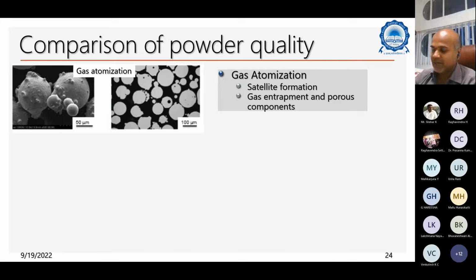Look at the quality of the particles here. So this is the gas atomized particles. I'm showing a 2D image of this here. You see these are the porosity that got entrapped due to gas entrapment. Gas entrapment leads to this porosity in the particles, and it gets translated to the final product as well. So what are the porosities you see in additively manufactured components? One source could be the powder, the porosity of the powder itself.